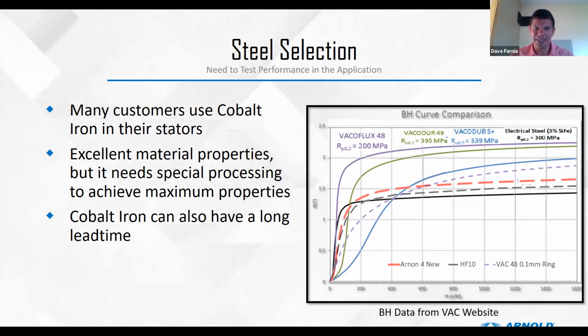If we're looking at the range of BH curves over here, again, Vacoflux is excellent. The base level M19 should be shown in black here. It's very common. It's available. It's inexpensive. It's easy to get a hold of. And so if you need a proof of concept demonstrator, M19 is a very nice path to go. If you're looking for that high performance, you can go to cobalt iron, but again, it's going to take some time and special processing considerations.